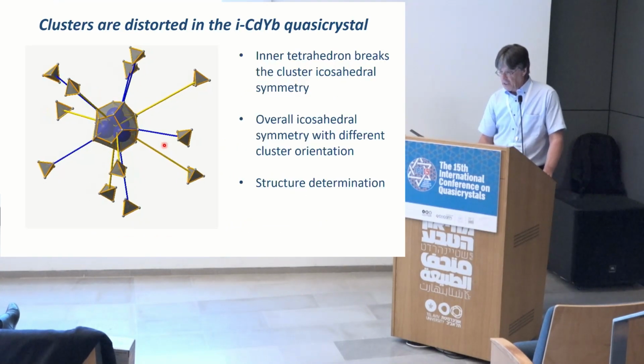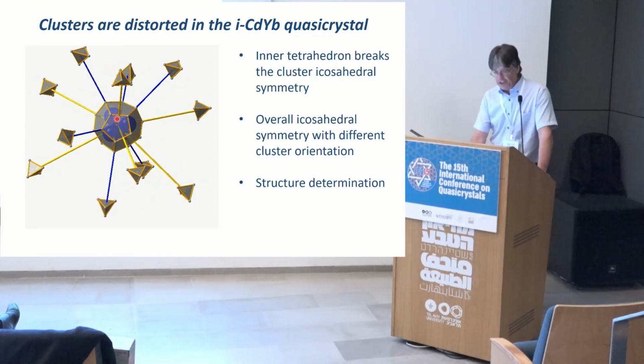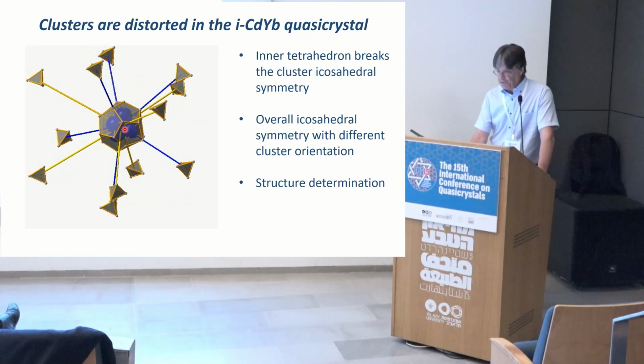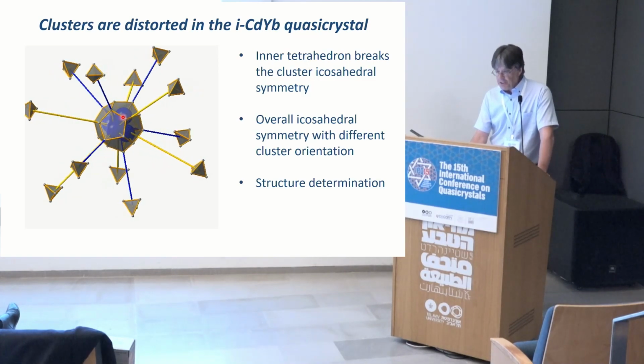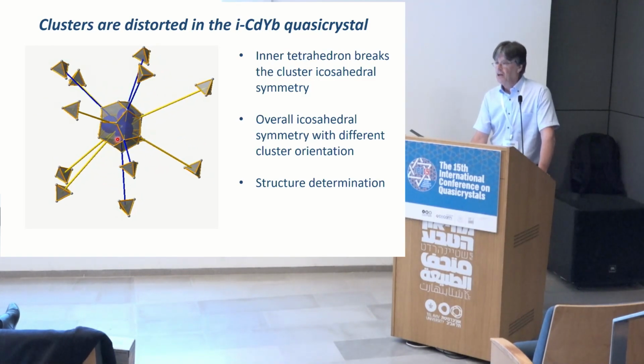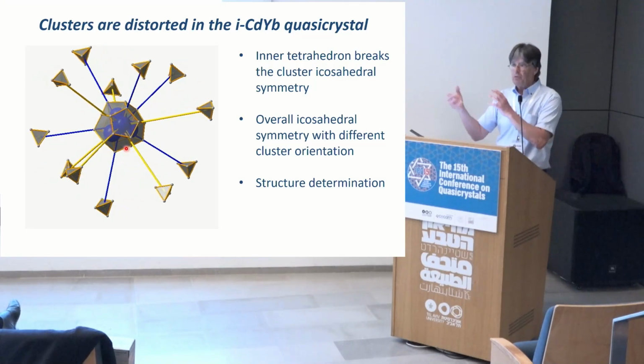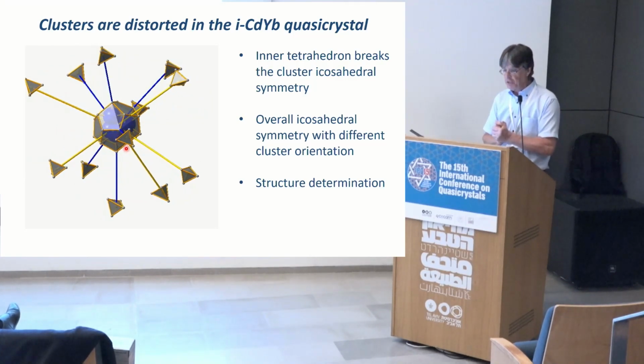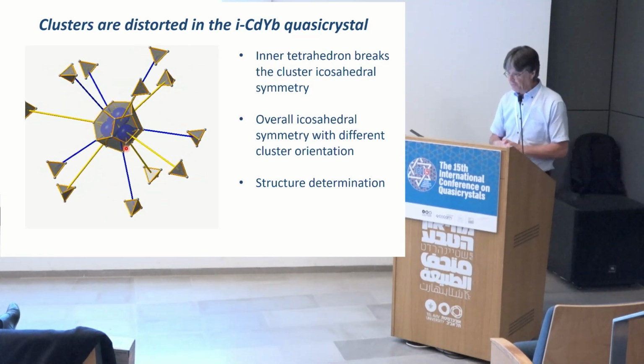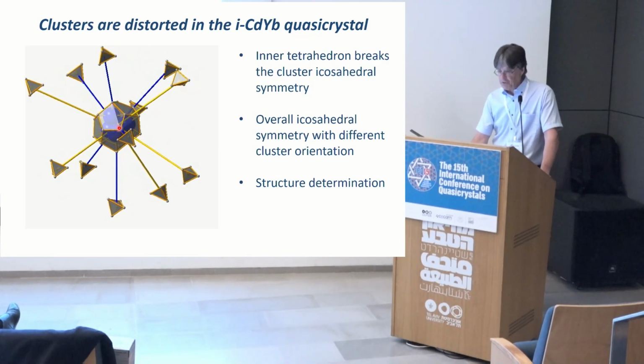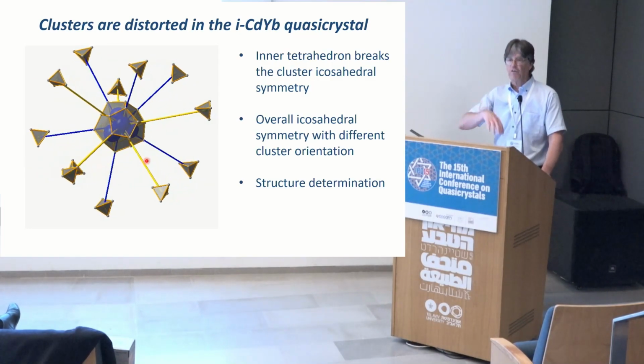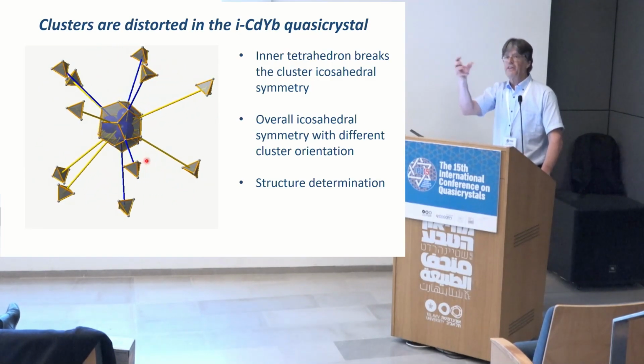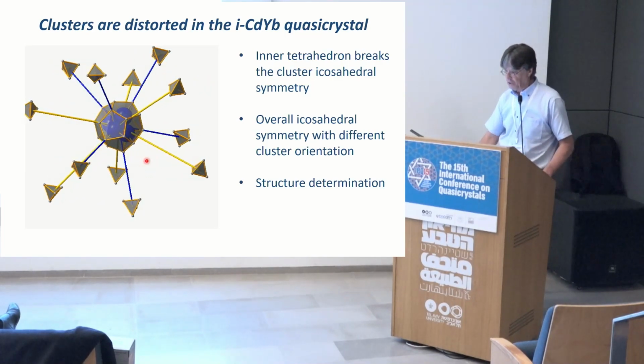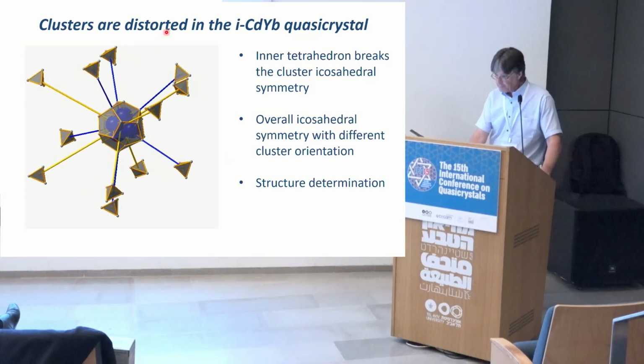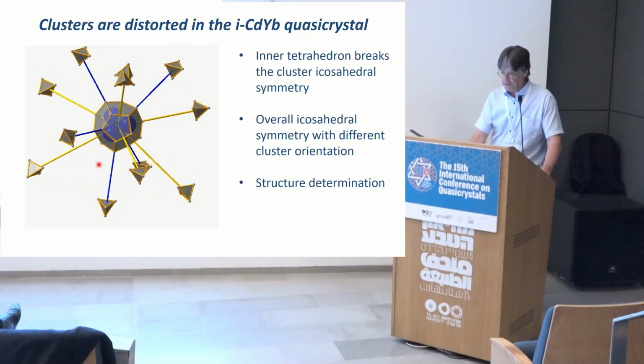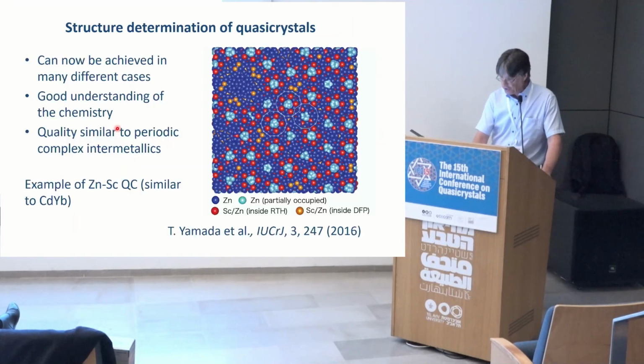And finally, the last point that was really a surprise when we derived the structure of this system: the central tetrahedron is strongly distorting the outer shells. So initially we thought that all the clusters should have icosahedral symmetry. Actually, it's not necessary, and indeed, they don't have icosahedral symmetry. The icosahedral symmetry is only recovered because we have all the orientations of this cluster with respect to the icosahedral point group. So the overall icosahedral symmetry is still preserved, but locally we have a strong distortion.